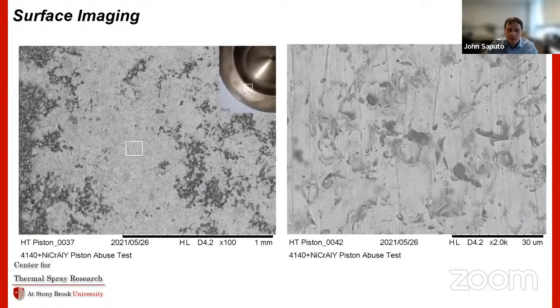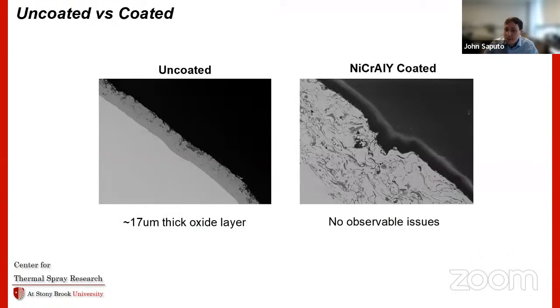You can see some of this soot buildup along the outer periphery of the piston. That's what you're seeing, those black spots in that left micrograph. And on the right, you see a higher magnification image, and you can see the finishing marks on the surface. Those finishing marks come from when we're polishing these things to make them smooth so they don't interfere with combustion. And it's great that you can see them because it's telling you that not a lot is happening on the surface of these things. You can directly compare the NiCrAlY coated and the uncoated piston, and you see none of that oxidizing damage that you would see in the uncoated piston, which is great. All those issues just kind of go away.